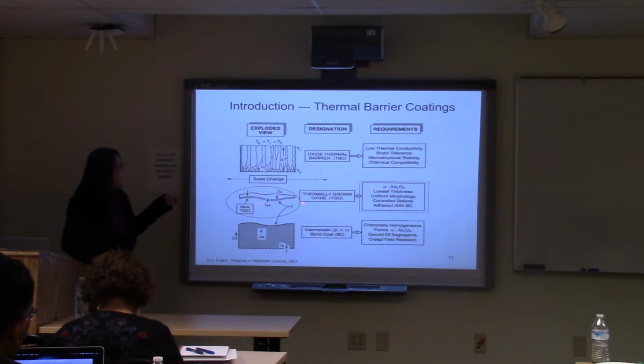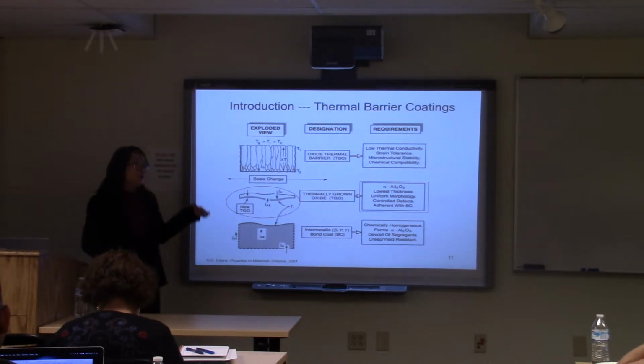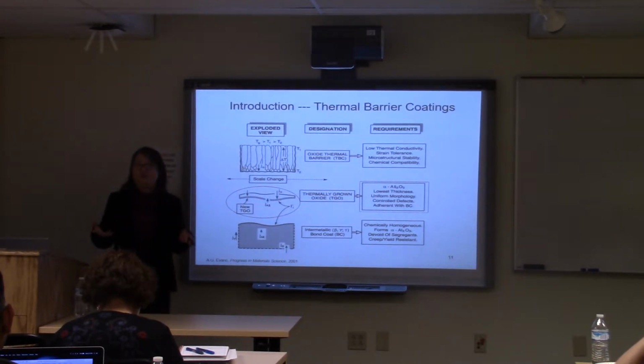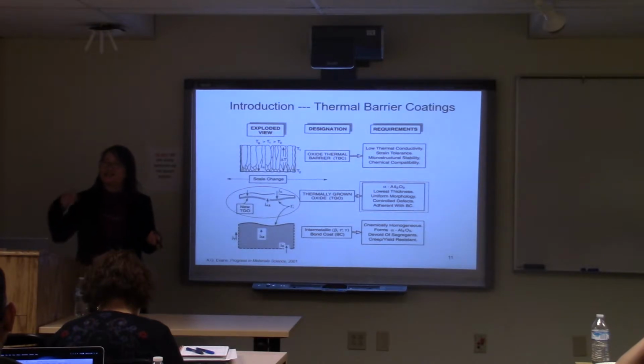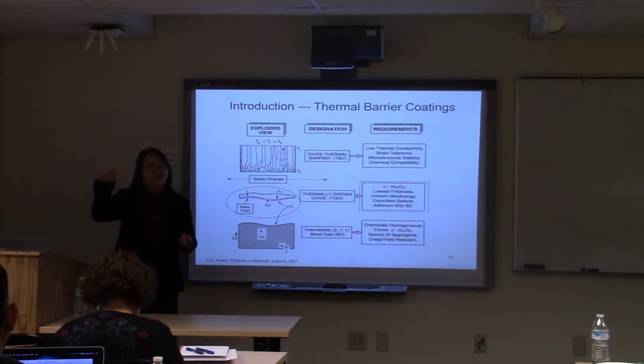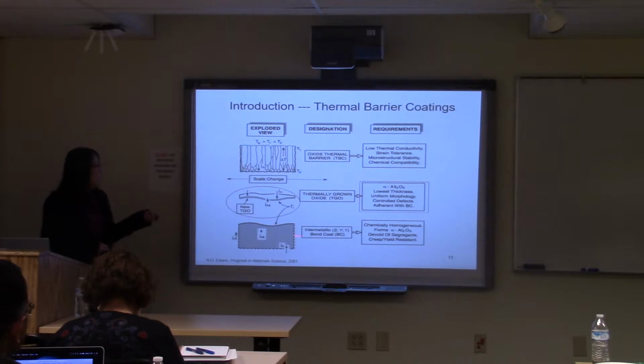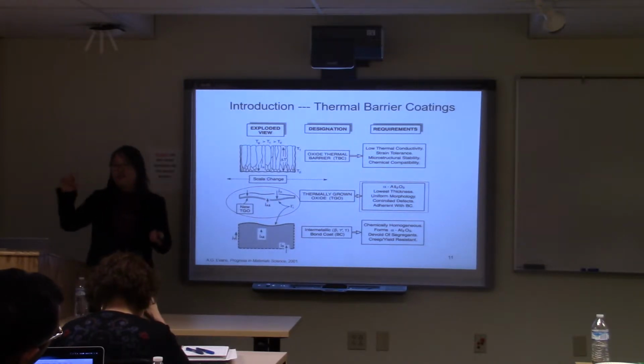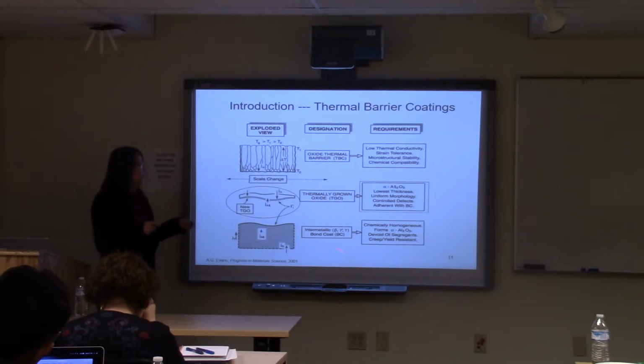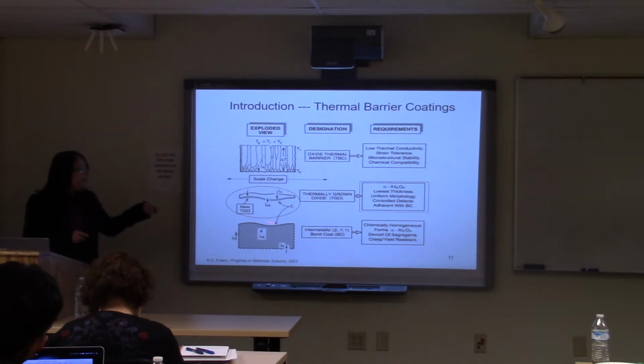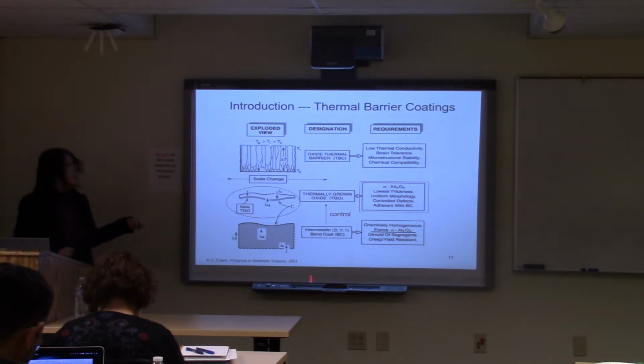Ideally, we hope this oxide layer will be a pure alumina, because alumina is a kind of self-oxidation terminating material. So once you have a thin and homogeneous layer, it can prevent further oxidation into the substrate here. And we also want it to grow homogeneously to reduce the stress created during the formation of this oxide layer. And this oxidation behavior is controlled by this bond coat.